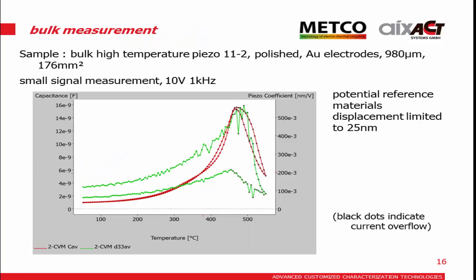And this is a bulk sample which we also measured in the DBLI system at a low field, like 10 volts and 1 kilohertz, and we could see that up to 550 degrees C, at the turning point here, the black dots mean that it's running into compliance because we only have 1 kilohertz, but it's much different from the resonance at high frequency. For an actuator, for example, you would have lower excitation frequencies and also different behavior.